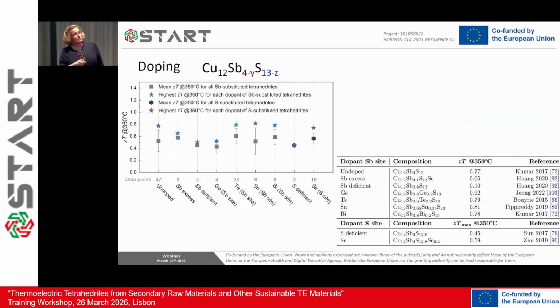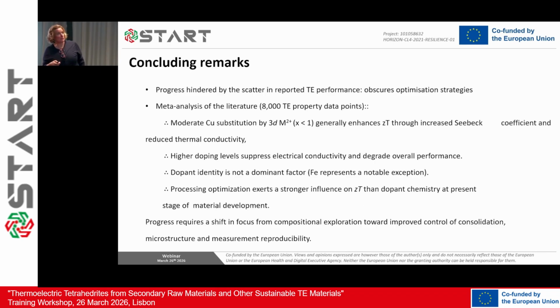There's also much less work done on substituting antimony and sulfur. Again, you see that the properties are not really the average and the peak — they're very scattered, so it's difficult to choose one doping strategy.